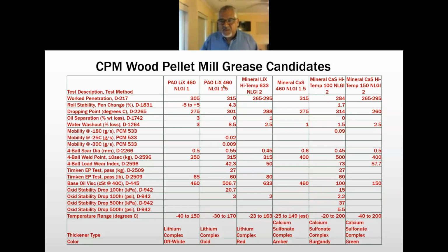The winning candidate was the calcium sulfonate complex grease with 100 centistoke base oil, with a much better load wear index and 4-ball number, and a pretty darn good 4-ball scar diameter.